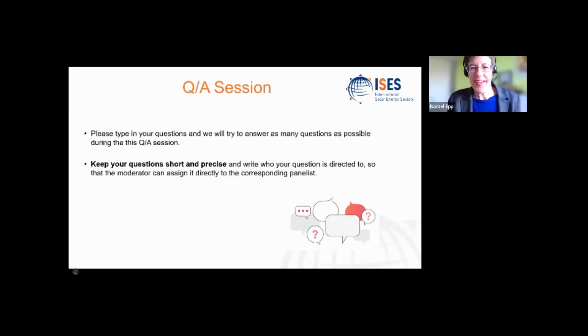Yeah. Okay. I think this could be also a question to you. What makes PCMs have different phase change enthalpies and temperatures in general? Yeah, it's mainly a structural question. So a good example, I think, are polymers. When you melt or crystallize polymers, then it strongly depends on the thermal history of the material. For example, when you crystallize a polymer from the liquid phase to the solid phase, and you use very, very slow cooling rates, the material has a long time to rearrange. So the structure and the entropy is getting higher and better. And when the structure is getting better, then the melting enthalpy is getting lower. The more unstructured your material is, the higher the melting enthalpy gets. So that's the difference in the enthalpy you see, for example, in polymers.